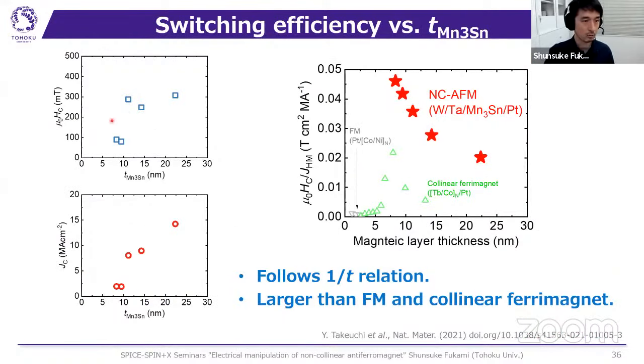So we studied it, and we prepared several structures with different thicknesses of the manganese tin, and we measured the coercive field and the critical current density as a function of the thickness of the manganese tin. We plot the coercive field divided by the threshold current density as a function of the thickness of the manganese tin. The obtained results are plotted by the star symbols. As you can see, for the non-collinear antiferromagnet, the results follow the 1/T relation. But the more interesting thing is that the efficiency is much larger than in the ferromagnetic systems and collinear ferrimagnetic systems.